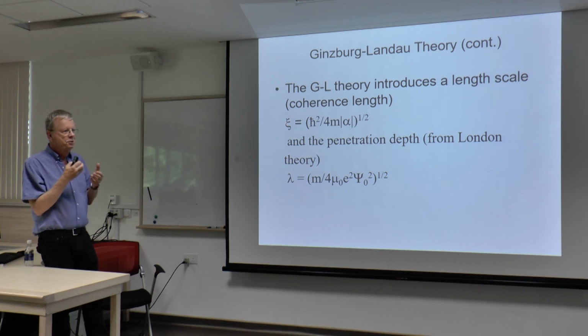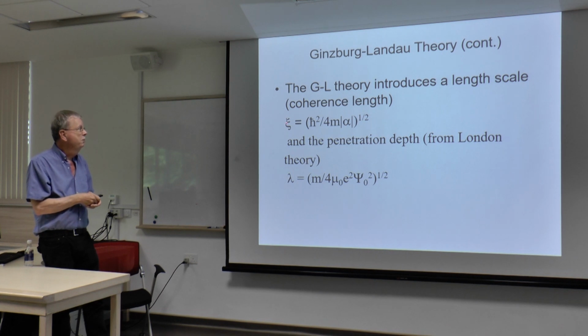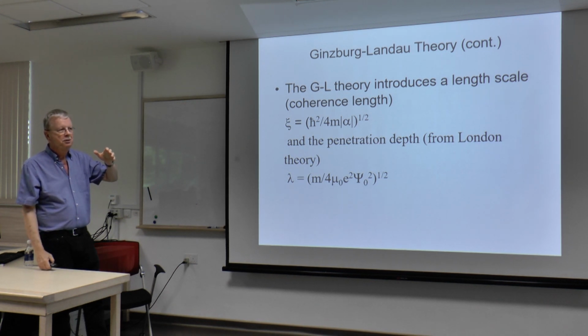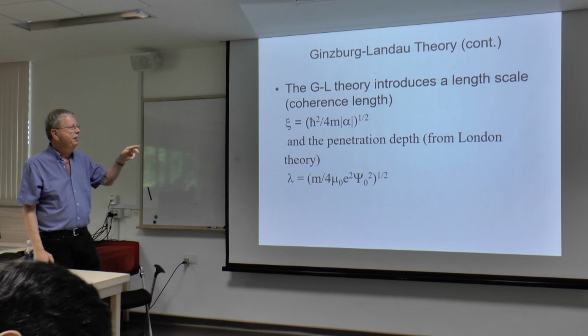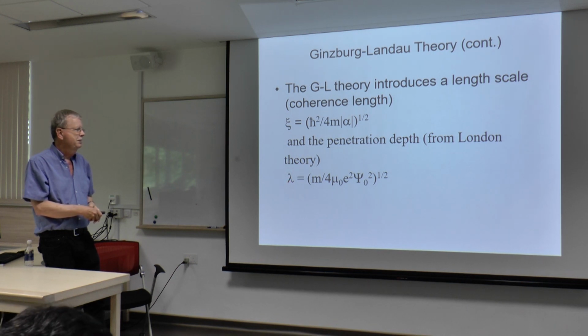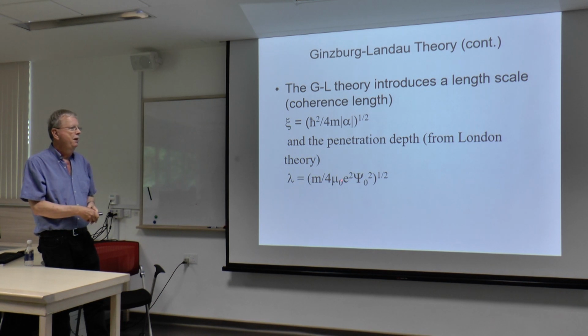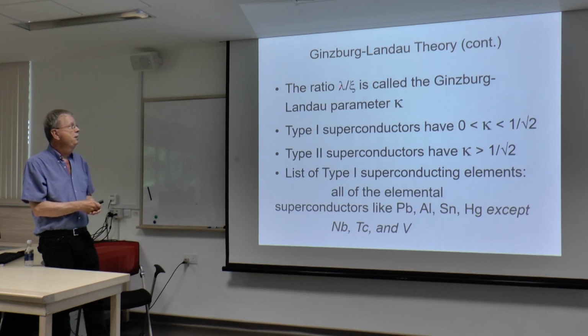The coherence length: if you have a superconducting electron pair, and they have some pairing interaction, let's not argue about what the pairing interaction is, but you want to know how far apart the electrons in the superconducting pair are coherent with each other in some quantum mechanical state. It's this number, which can be rather large in terms of lattice spacing. And if you put a magnetic field on a superconductor and the superconductor expels it, it's not a discontinuity at the surface. There's some penetration of the field. There are some surface currents doing the shielding, and that penetration depth can be thousands of angstroms. So making a thin film less than the penetration depth, you can run your critical behavior upwards. The ratio between the penetration depth and the coherence length is called kappa.